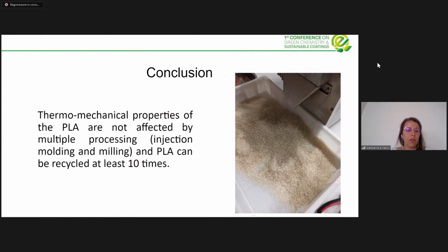As far as we analyze all the results, we can say that thermal and mechanical properties of the PLA are not affected by multiple processing. So both thermal and mechanical, injection molding and milling. And PLA can be recycled at least 10 times. So we went up to 10 times of reprocessing. We don't know what will happen after that.